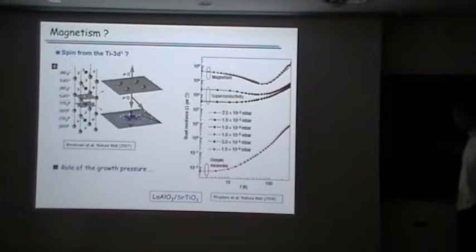This is still controversial. Remember, depending on the pressure you grow your structure, you can have different behavior. And this has been, for instance, mentioned and put forward in this paper. If you have very, very low pressure for growth, you are full of oxygen vacancies, and you see the resistivity of the pressure is very, very low. So this is a regime. In this case, it's really a 3D fully conducting strontium titanate substrate. The range where you see superconductivity is this one.